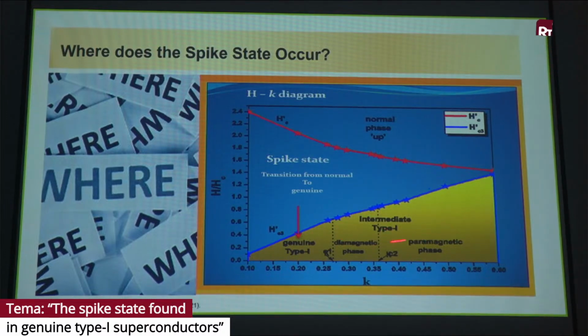In the intermediate type 1 superconductor, we have two phases: the diamagnetic phase and the paramagnetic phase. It is important because there is a competition: a giant vortex is created inside of the needle, opposed to this vortex in one direction, and the supercurrents at the edge of the needle are in another direction. This competition shows us whether it has a diamagnetic or paramagnetic behavior. Well, so where does the spike state occur? It occurs only in the region from the normal state to the genuine type 1 superconductor.